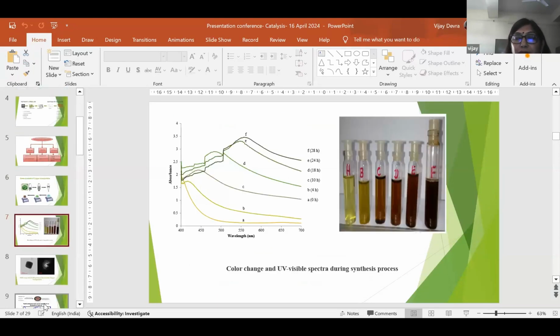Then the synthesized copper nanoparticles were characterized by different instrumental techniques. As you can see, the different colors of the suspension of the nanoparticle confirm that as time passes, the color of the solution changes. Finally, we get the dark brown color, which indicates the formation of the copper nanoparticle. That is confirmed by the UV visible spectra. UV visible spectra show the absorbance at different wavelengths at different intervals of time. As time passes, the wavelength of the nanoparticle increases. Finally, we get 570 nanometer, which confirms the formation of the copper nanoparticle.